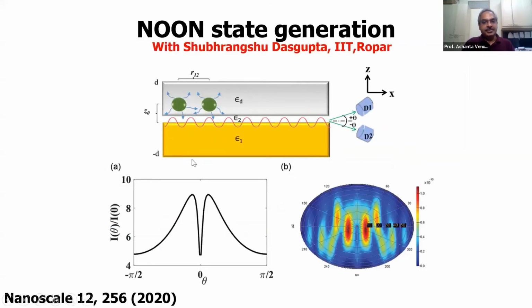So there is another one, a more recent one, the so-called NOON state generation. This is a non-classical state of light where whatever photons are emitted are all either in state 1 or in state 2. For example, in this geometry, we have two quantum dots in close proximity to a metal film. When you excite one of these quantum dots, it emits a photon that excites a plasmon at the metal-dielectric interface, epsilon 1, epsilon 2 interface. This plasmon is going to excite the second quantum dot, or it could be the other way.